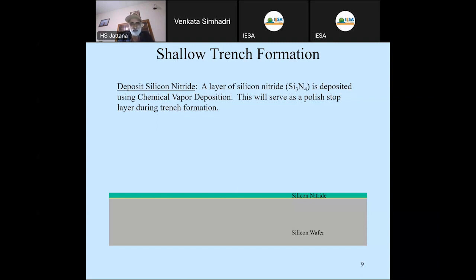They are close to 800 micron. We were using an 8-inch, 725 micron thick wafer. And you see, this is the thickness of the wafer, and processing is done only at the top, in the polished side, and the transistor will be just in the top 2-3 micron surface that is useful.